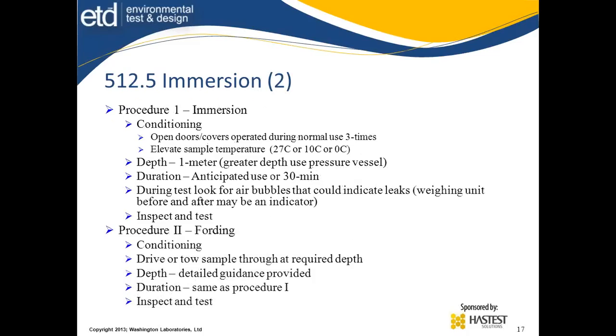The procedure calls for conditioning and opening the doors and covers operated during normal use 3 times. Elevate the sample temperature either 27 degrees C, 10 degrees, or nothing, depending on how it's used. Immerse into a depth of 1 meter or greater depth. You'd need to use a pressure vessel to expand the pressure on this, or you could go to a deeper place if you have it available. The duration is the anticipated use, or 30 minutes.